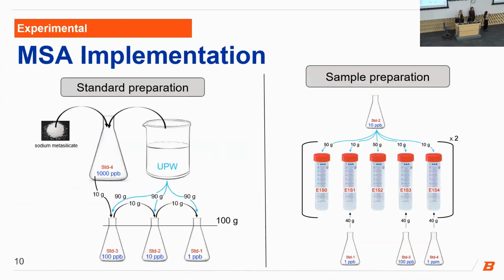And to get the concentration of the unknown, we look at the x-intercept, which equals negative y-intercept divided by the slope. So for MSA implementation in our experiments, we prepare a series of dilutions using ultra-pure water from the MilliQ system and sodium metasilicate. And we prepare 4 different standards of different concentrations, and one of them we treat as the unknown. And we intentionally prepare the unknown at a known concentration level because we wanted to see if our results match. And that will give us a confirmation that our method and measurements were working correctly.